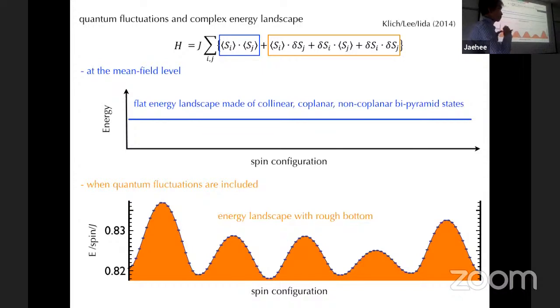Okay, now the microscopic origin of this complex energy landscape. When we say classical spin liquid in this kind of material, in fact, we are only considering the zeroth order spin Hamiltonian. If you only consider the zeroth order, mean field level, and then plot the energy landscape as a function of some kind of spin configurations, then we'll have this flat energy landscape made of collinear, coplanar, non-coplanar bipyramid states.